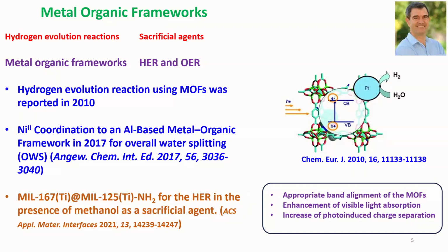So this was reported in Chemistry-A European Journal. And lately, the next example appeared, constructing two MOFs, one MOF as a core and the other MOF as a shell. This MOF was constructed for the hydrogen evolution reaction, and this was reported in ACS Applied Materials & Interfaces. So the key point here is that if you want to develop a MOF-based photocatalyst, one has to consider designing an appropriate band alignment in the MOF.